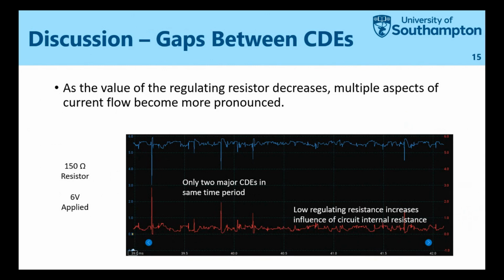There are only 2 major discharges and 2 extra slightly more minor ones recorded in the same 3 millisecond period, even though the charge rate's significantly higher. If it wasn't doing all this continuous current scenario, you'd be counting hundreds, if not thousands, of discharges if it kept the insulating property. But in this case, we get individual discharges and then continuous current for a significant amount of time until something happens.